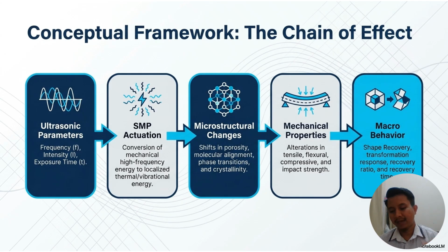When applied to an SMP sample, they drive SMP actuation, the conversion of high-frequency mechanical energy into localized thermal and vibrational energy within the polymer matrix. This localized energy input triggers microstructural changes, specifically shifts in porosity, molecular alignment, phase transition, and the degree of crystallinity. These microstructural changes in turn determine the mechanical properties of the printed sample, its tensile, flexural, compressive, and impact performance. And all of this feeds into the final behavior: the shape recovery ratio, transformation response, and recovery time. This is what we ultimately measure and optimize.